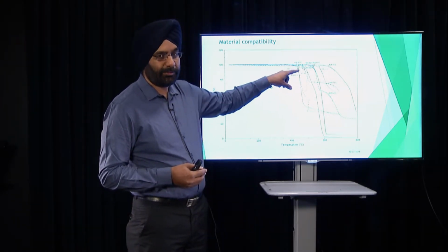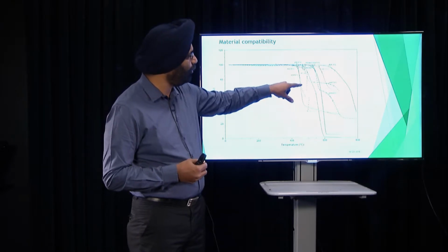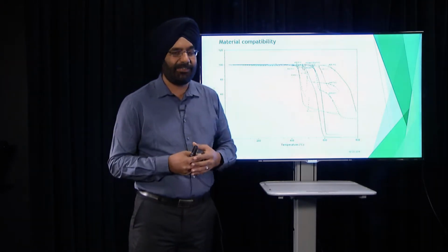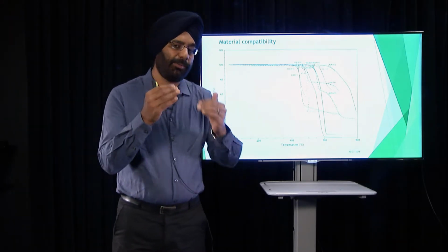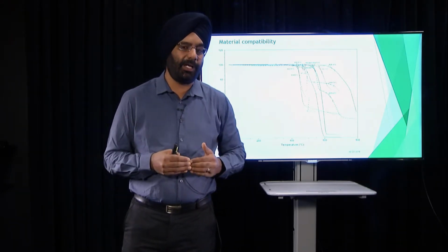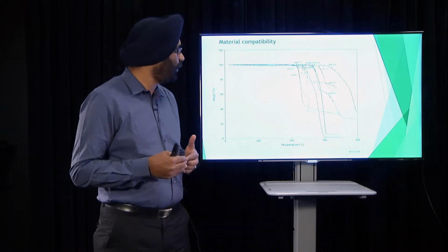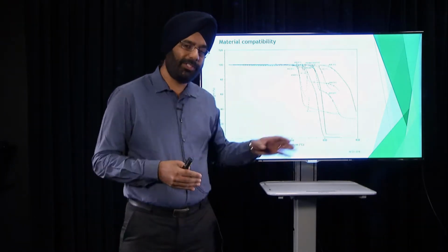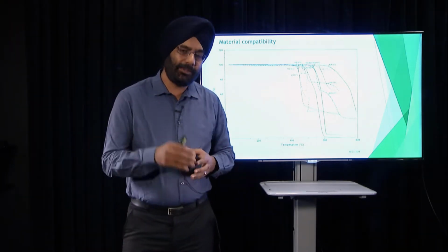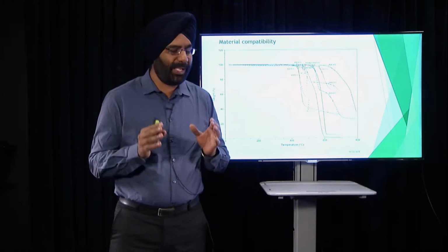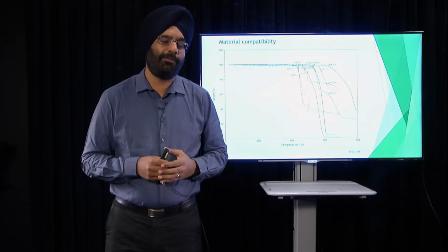but in the presence of the phase change material, the salt which we plan to use, the decomposition started at 465 degrees C. So the decomposition temperature has come down by close to 105 degrees C. This clearly indicates that the molten salt is reacting with this polymer. So we cannot use this polymer for encapsulating this material.